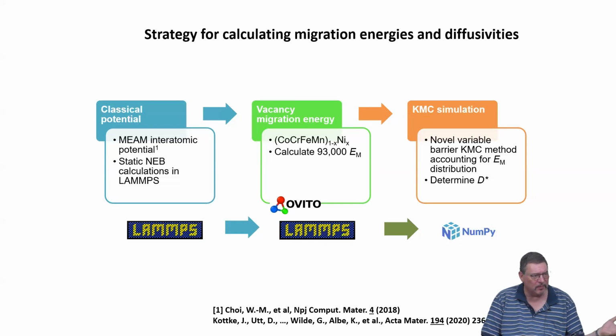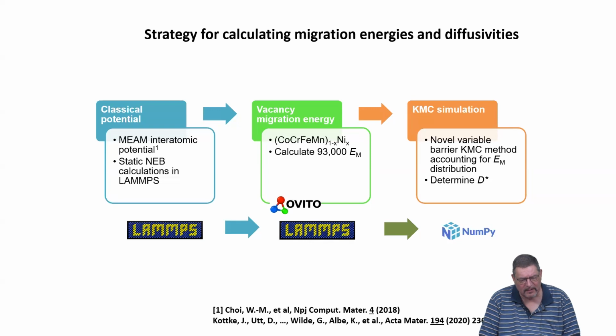So we were doing experimental, and they simulated basically the similar thing using atomistic simulations. And they basically use a MEAM interatomic potential, because for the 5-component systems you cannot get really a detailed potential, and use the typical LAMMPS software package in order to calculate molecular dynamics.